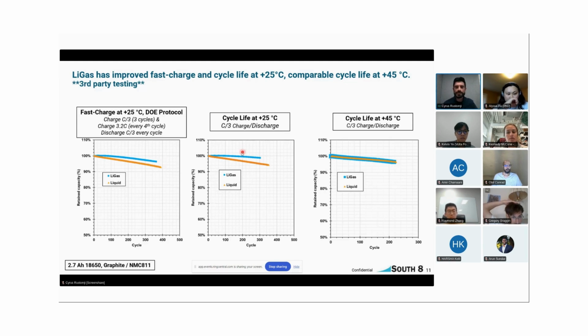Here's just your typical cycle life at C/3 charge and discharge, outperforming that liquid electrolyte. If you buy a commercially off-the-shelf cell from Samsung or Panasonic, this liquid electrolyte curve would be better, but this is actually just an R&D cell we procured from some partners at a low volume. So that's probably the reason why your cycle life on the liquid cell is not as great. And then at 45 degrees Celsius, we do have pretty much on par performance with that liquid electrolyte cell. So pretty good performance there at higher temperatures.